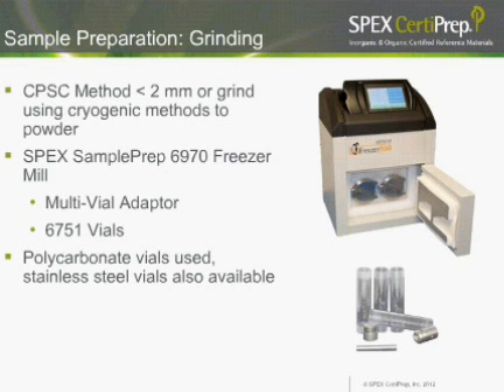We also decided to use a polycarbonate vial, and we did look into potential contamination issues, but we actually found no contamination issues by using the polycarbonate vials. If you do worry about polycarbonate adding phthalates or bisphenol A to your analysis, you can run a quality control blank sample alongside your toys, and that will give you a little confidence about the potential for contamination, or at least eliminate the potential for contamination. Or you can use a stainless steel vial. The only problem with the stainless steel is if you are going to follow up with metals analysis, you might have a new contamination issue to worry about.